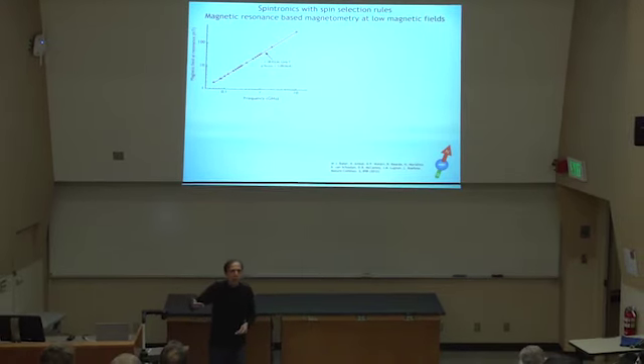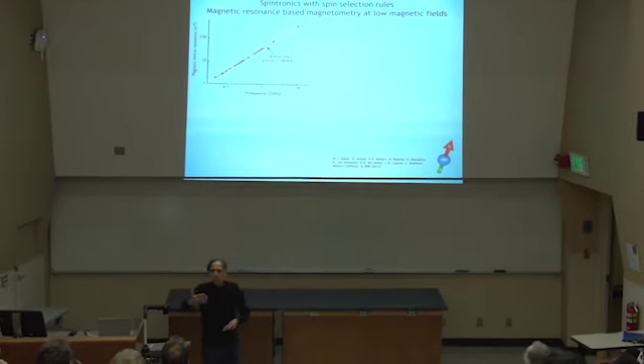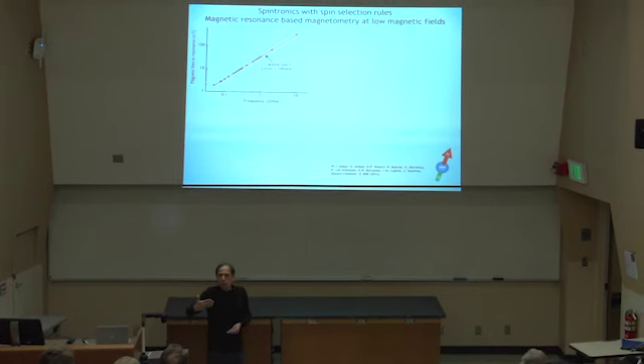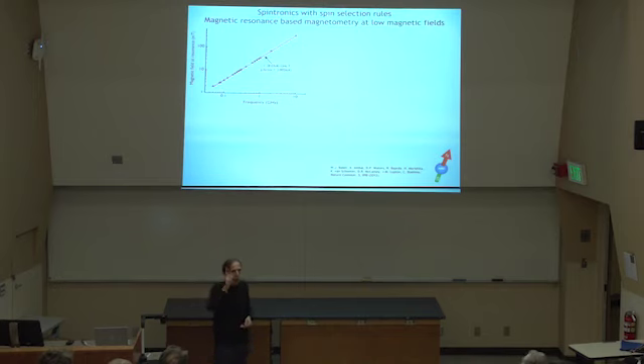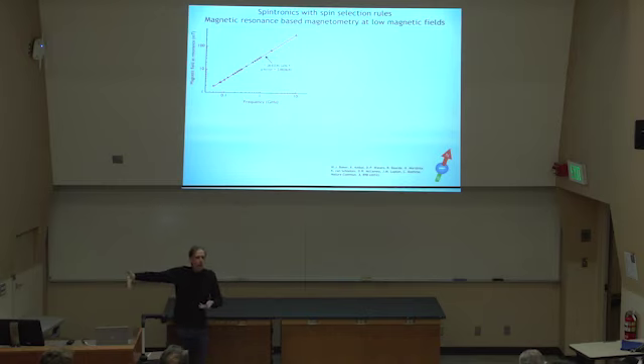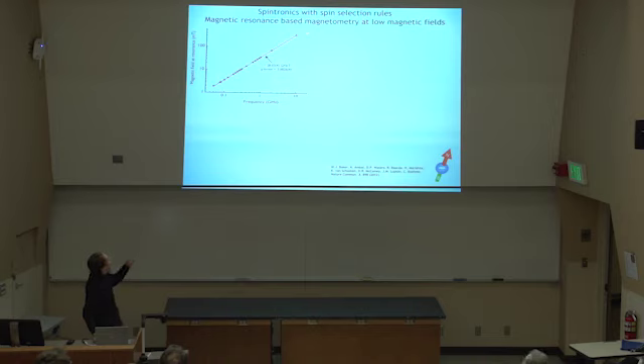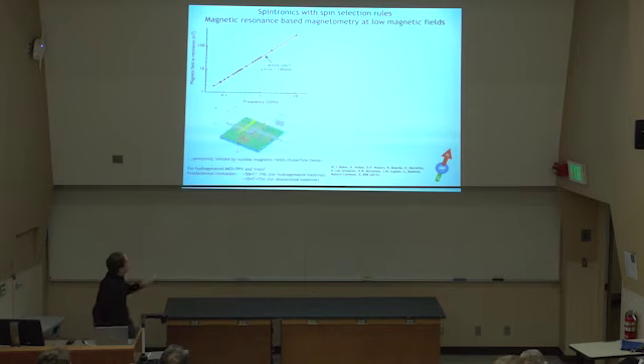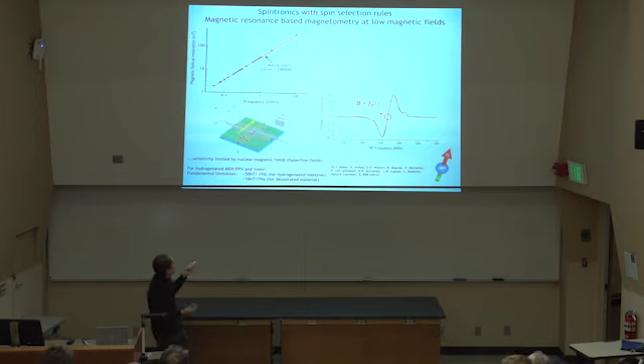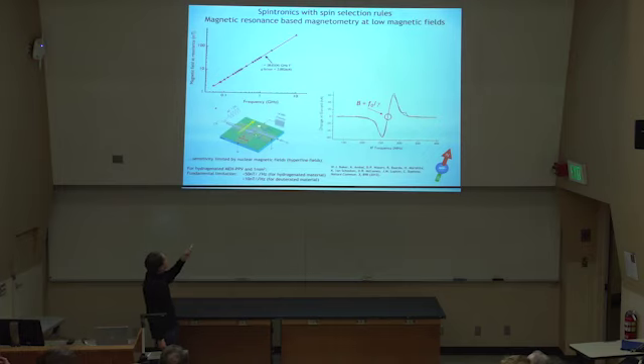Using magnetic resonance-based magnetometry is as old as magnetic resonance. People have been doing NMR magnetometry since, I would guess, the 1940s. No, actually, early 1950s. That's when this really started. But it's always been used at high magnetic fields. It's used for calibrations of NMR experiments. Now you basically can extend this linearity to really low frequencies and therefore magnetic fields and use it as a sensor. And because it's based on electric current measurements in thin film devices, you can implement this as a monolithic thin film device where you essentially have these bipolar injection devices that you combine with an RF source that is produced also by a thin film layer.